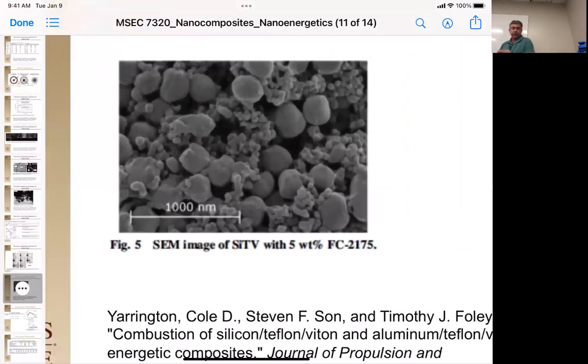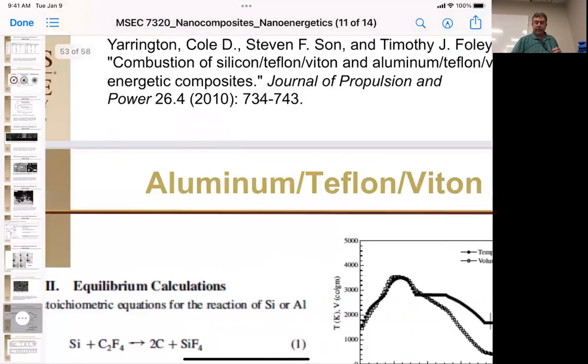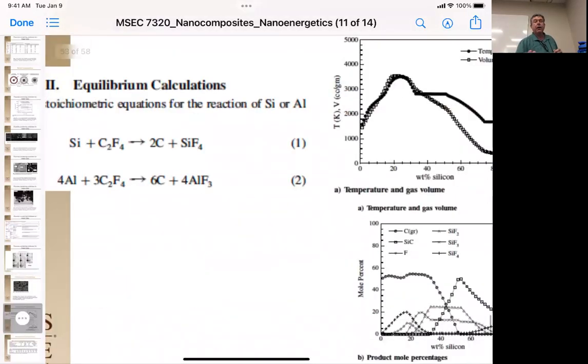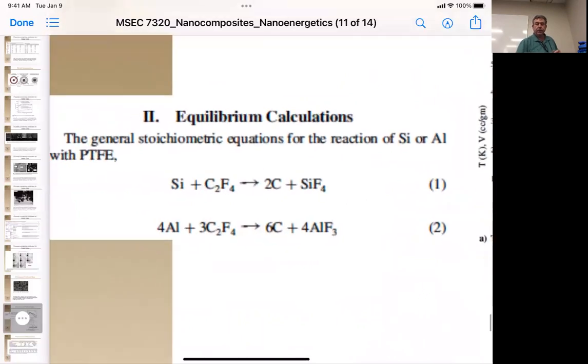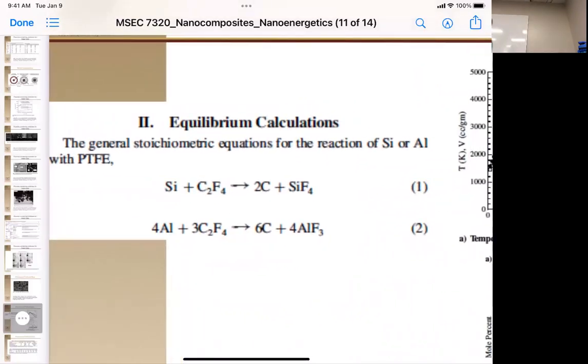This is, I think the larger particles are the aluminum, and then this is a fluorinated material here. I don't think we see any of it here, but it's in there. And so what they were able to do is build this by that spray type method. And oh, Nano Silicon, that's why, or aluminum. Okay. So the reason that they wanted to use the aluminum or the silicon is because if you look at